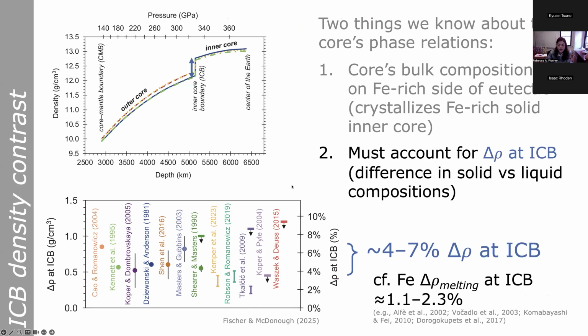Okay, and the other kind of constraint on the phase relations. The difference in composition between the solid and liquid has to account for the density difference between the inner and outer core at the inner core boundary. So this blue arrow here in the upper figure, this density jump at the ICB is what we're trying to explain. The figure on the bottom is a summary of a bunch of different estimates from seismology on what this density difference is at the inner core boundary. These studies use very different seismological methods. Some of them only give an upper bound shown with the arrows. Some techniques are a lot more sensitive to this property than others. I've just sort of plotted them all up here.